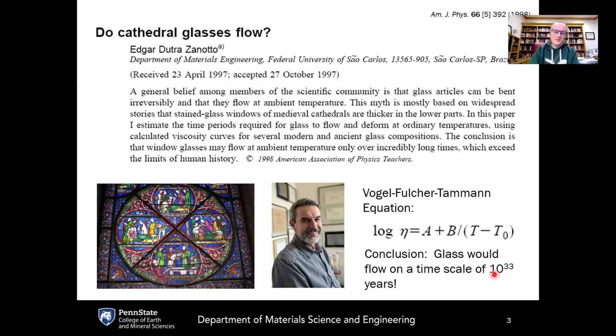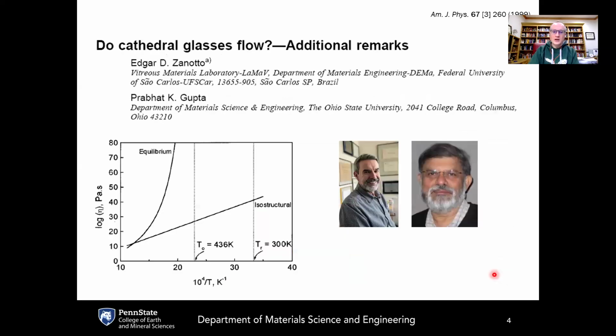Now, this paper generated a lot of attention. One of the readers who considered this very carefully was another good friend of mine, Professor Prabhat Gupta from the Ohio State University. And one of the things that Professor Gupta noted is that that VFT equation, which shows the log of the viscosity versus inverse temperature, this really only captures the viscosity of the supercooled liquid state. And what actually happens is that as the supercooled liquid is cooled through what's called the glass transition range, which occurs at a viscosity of about 10 to the 12 Pascal seconds, it's no longer a supercooled liquid.